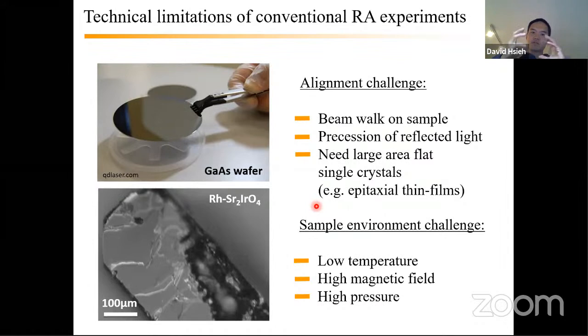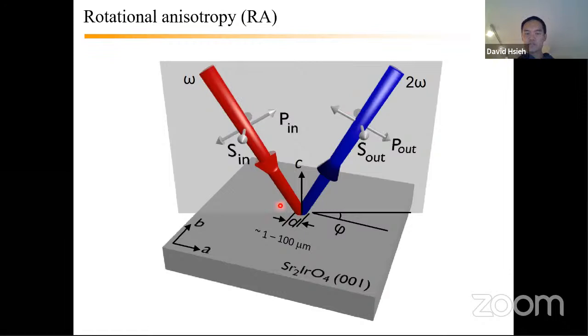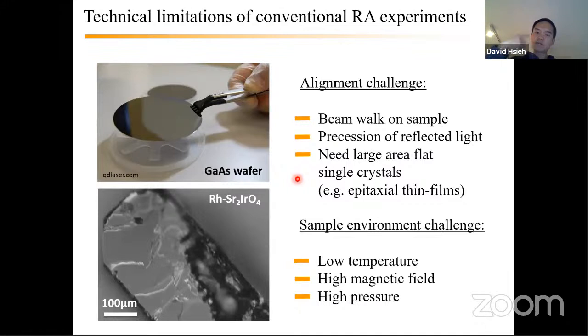You have to avoid beams walking around the sample, going to bad spots. You have to avoid any precession of the reflected beam, right? So you want to keep this angle of incidence, okay, and angle of reflection constant as you rotate phi, okay, because it turns out the SHG intensity is also very sensitive to this angle of incidence. And so if you have any precession in your reflected beam as you're rotating the scattering plane, you're also going to get artifacts that obscure the true symmetries. Okay. And as I mentioned before, if you're dealing with small crystals, which you typically see in these correlated materials, you've got to have that degree of control.